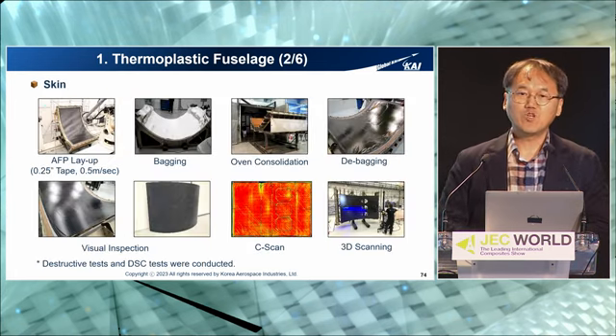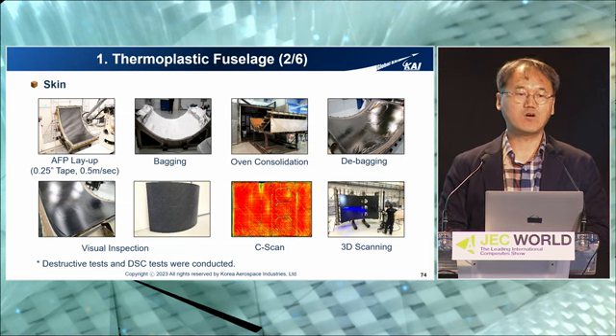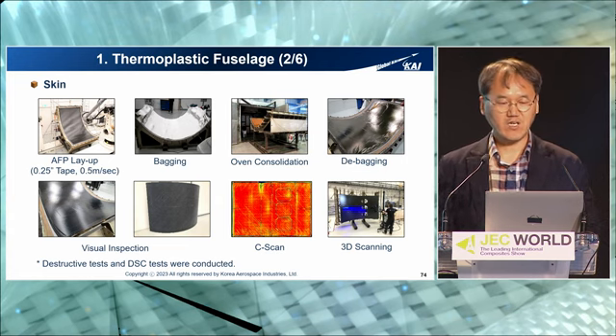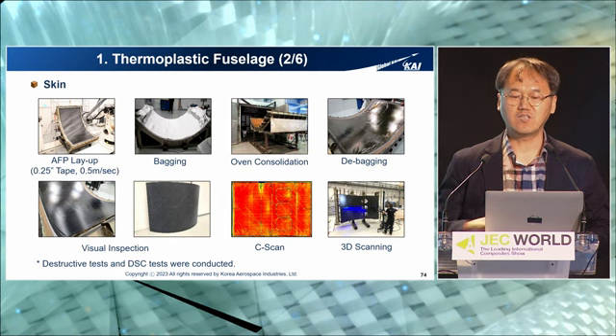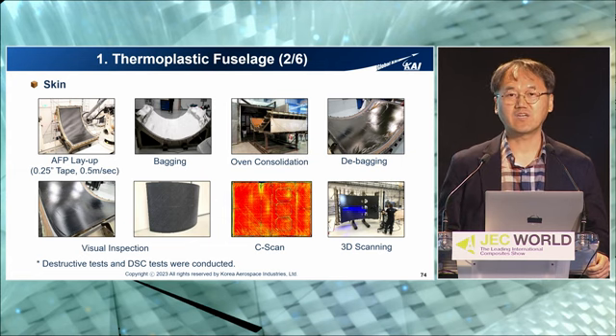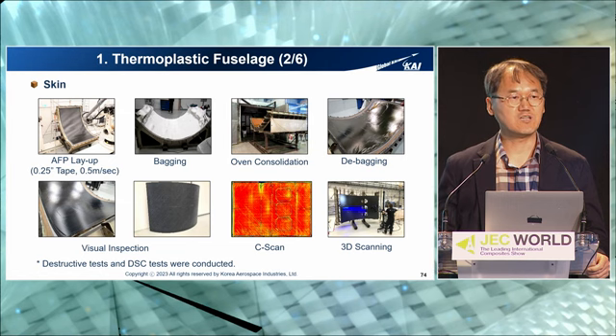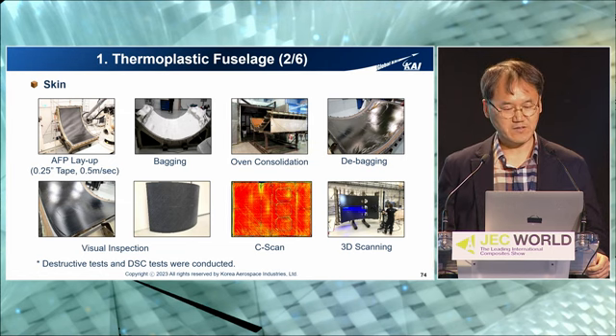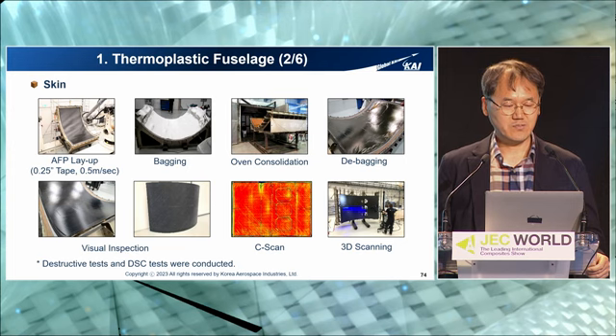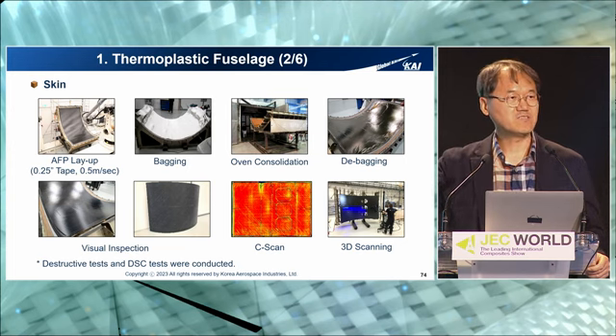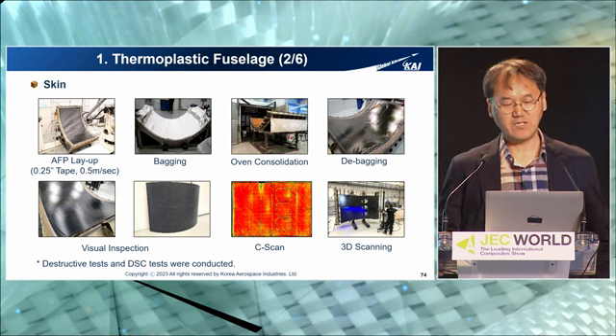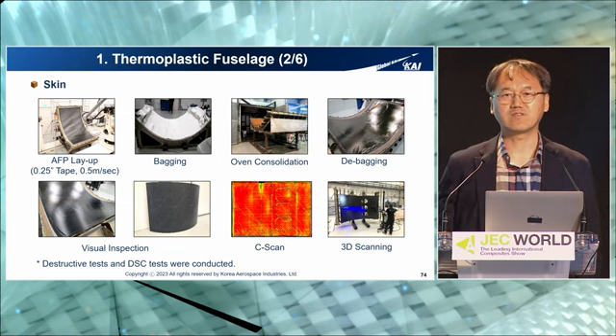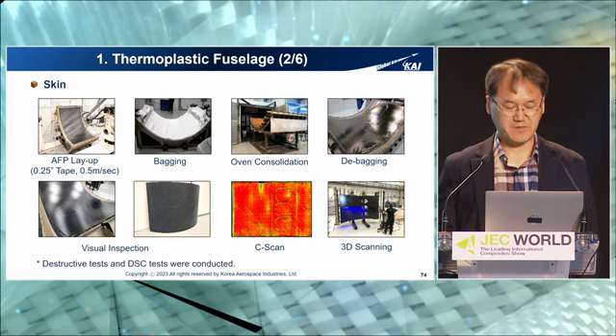This slide shows the skin manufacturing process. We selected 0.25-inch tape, and the AFP speed is 0.5 meter per second. And you can see the bagging process and oven consolidation process. We conducted C-scan to scan for internal defects and 3D scanning to check the final part design, dimension and tolerance. We also conducted a destructive test to check the inside part quality, and DSC tests were also conducted to check for cold crystallinity.